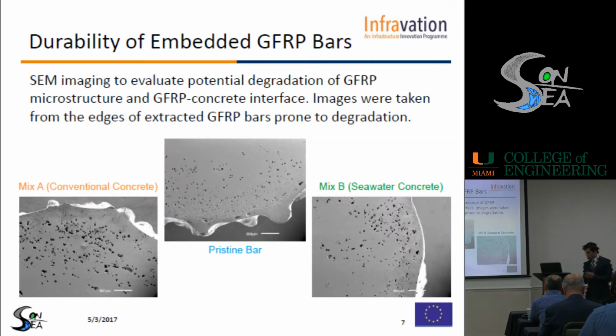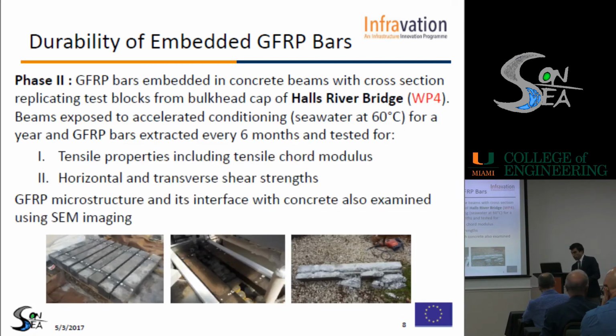We wanted to make sure that everything is all right in the microstructure as well. So we did some SEM imaging of our extracted bars. As you can see, mix A, which is the conventional concrete, is the bar that I extracted from mix A. And this is the pristine bar. This is the bar that you get from the manufacturer right after they produce it. And this is mix B, the bar that I extracted from seawater concrete. And you can see no degradation, basically. So this one was phase 1.